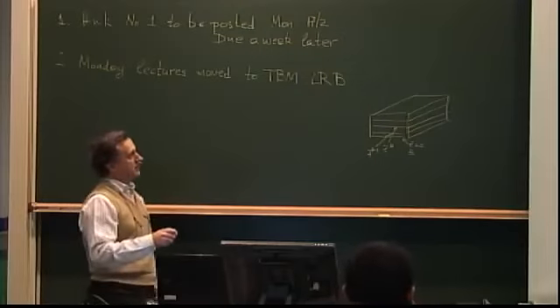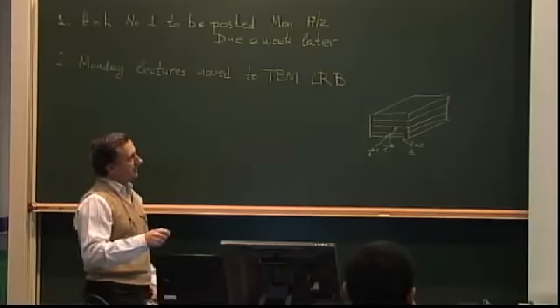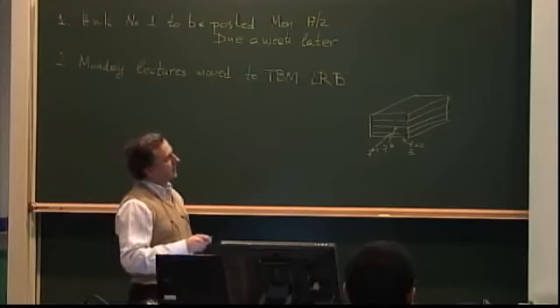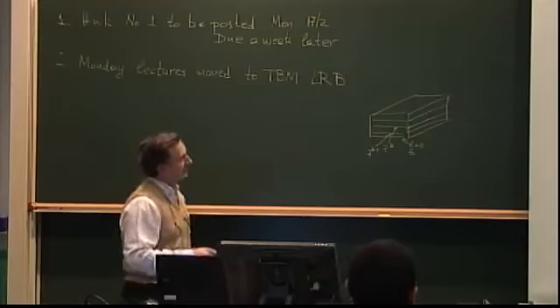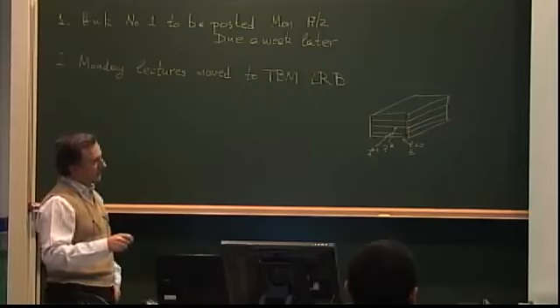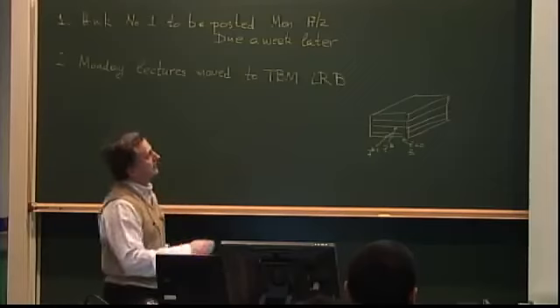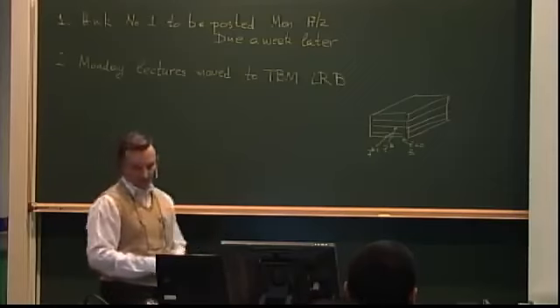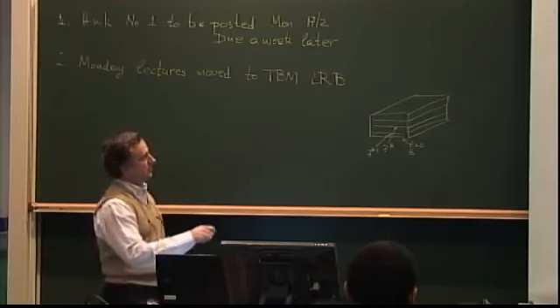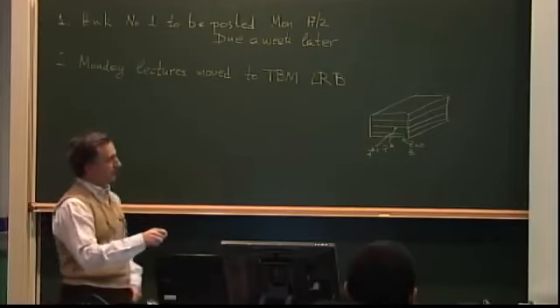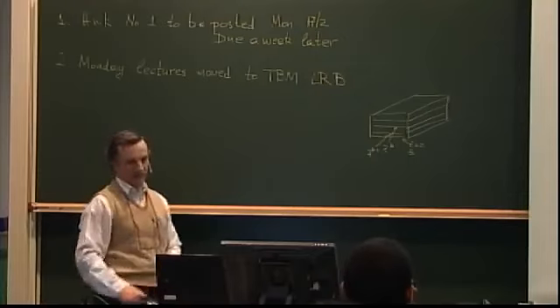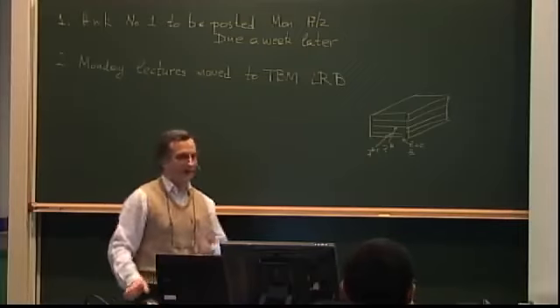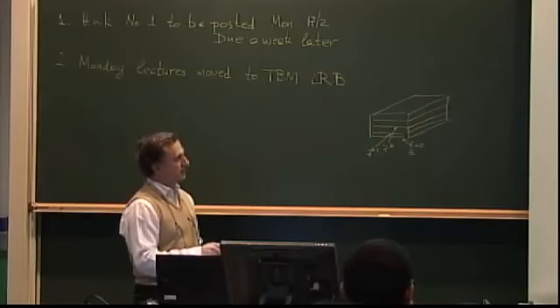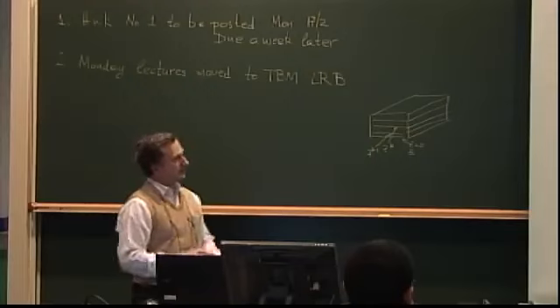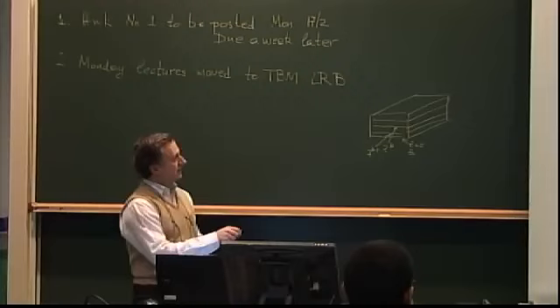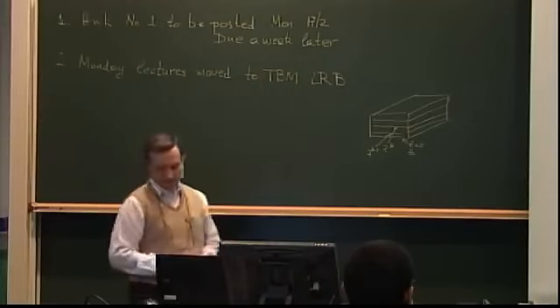So I basically take that first relationship of those equations and I multiply by z and integrate, and we would get this plus additional terms. I forgot to say plus here, additional terms. But this is the strain now, epsilon. Z times this second derivative with a minus sign is the epsilon x strain, which is shown right there. So this is the mx by definition. And in the general case, when we have the epsilon x, the epsilon y, and the gamma, the kappa x, kappa y, and the kappa xy, we will generate the general relationship which involves q11, q12, q16. The 2 here comes from the fact that our curvature relationship here for this twisting strain involves this factor of 2.